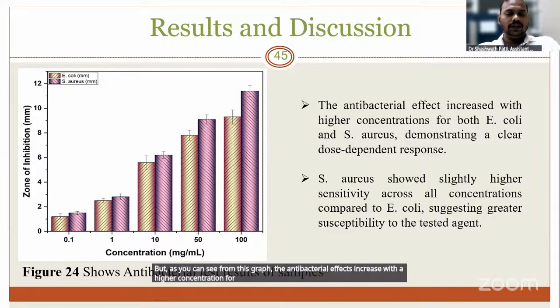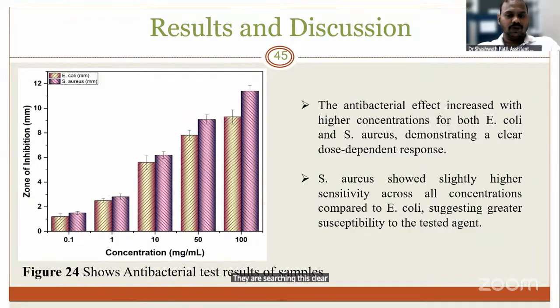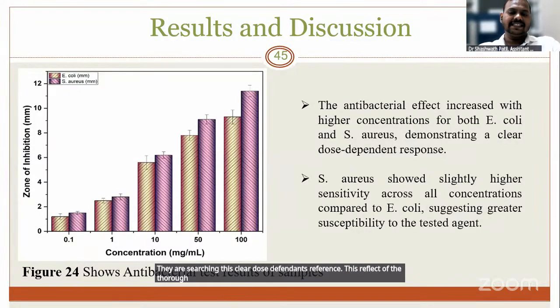As you can see from this graph, the antibacterial effect increased with higher concentration for both E. coli and Staphylococcus aureus bacteria, demonstrating a clear dose-dependent response. Staphylococcus aureus shows slightly higher sensitivity across all the concentrations compared to E. coli, suggesting its greater susceptibility to the tested agent.